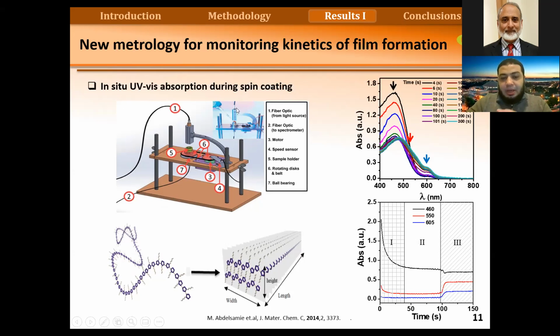So I made a new technique that can help us watch the changes in the film during spin coating. We start with, for example, a polymer material or small molecule material that is dispersed in a solution, and then we spin coat to form a film. This technique can help us see this transformation from the solution to the solid state. As we can see here on the right, I'm probing the absorption at different wavelengths. These colors correspond to these colors. So we can see the absorption.